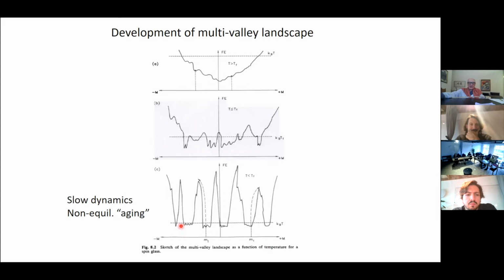The breaking of replica symmetry requires this. I can look at a single valley here. I see the mini valleys. My system is fluctuating around here. I get some time delays, even at low temperatures. I get the slow dynamics. And what I need to do then is to look at the overlap of these valleys. If I get a distribution of overlaps of these valleys, I am generating then the equilibrium state of the spin glass. If I sit in a single valley and look at the behavior of a single valley, I'm using effectively the single-valued Edwards-Anderson order parameter, which is a short time scale replica. So this is what we are getting now.